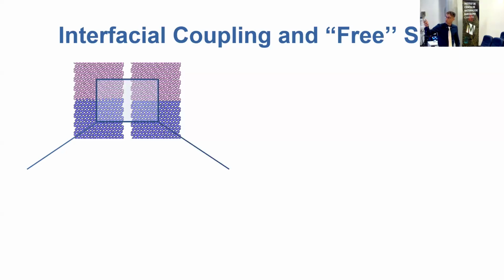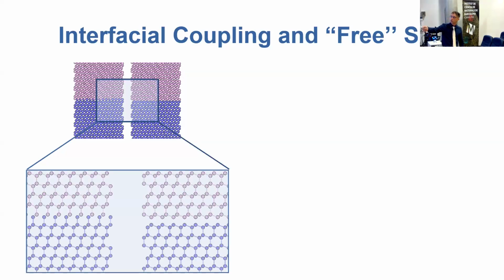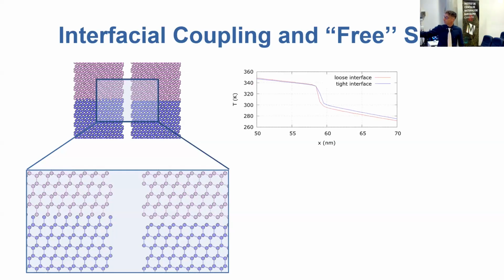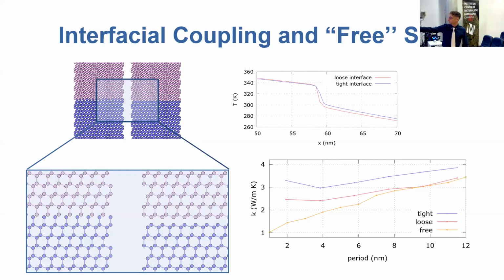Here, if you zoom on the interface region, you can appreciate that the coupling between silicon and germanium atoms is different in the two configurations. And this yields a different thermal boundary resistance in the two cases, which then yields a different thermal conductivity for the two cases. And you can really appreciate that there is sort of a rigid shift between the thermal conductivity as a function of the superlattice period for the tight and loose interfaces. I call them tight and loose just because here it looks tight and here it looks loose.